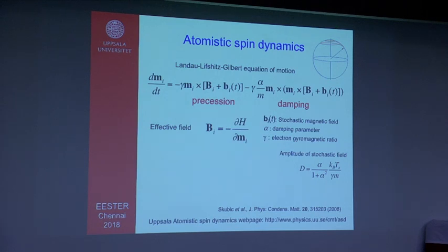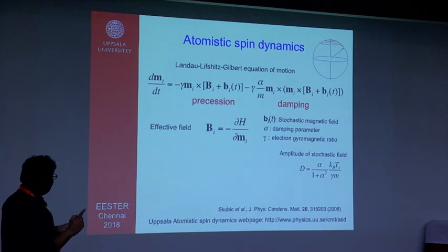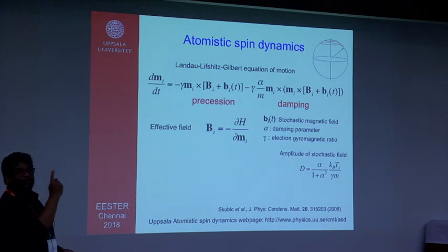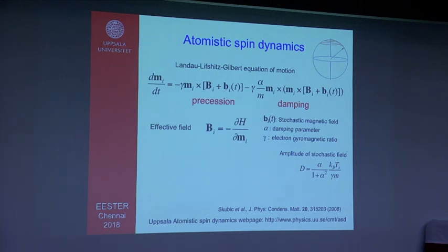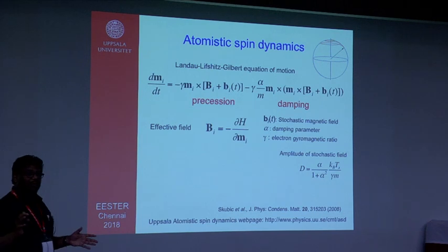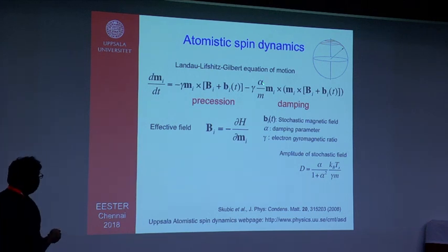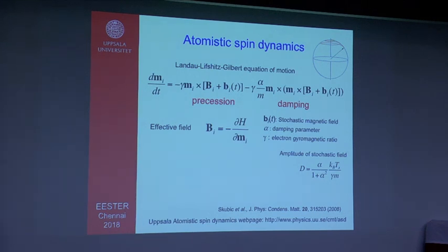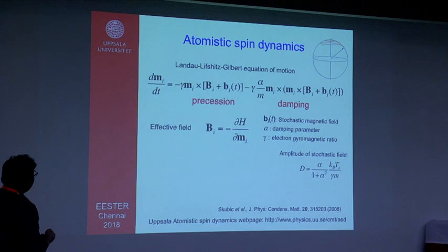If you only have the precession term, it will not decay, it will not be aligned with the effective field. You need this damping term in order to have this moment slowly come and become aligned with the effective field. This is all about the so-called Landau-Lifshitz-Gilbert equation. This alpha is called the Gilbert damping parameter, which plays a very important role in how slow or how fast this is going to happen.